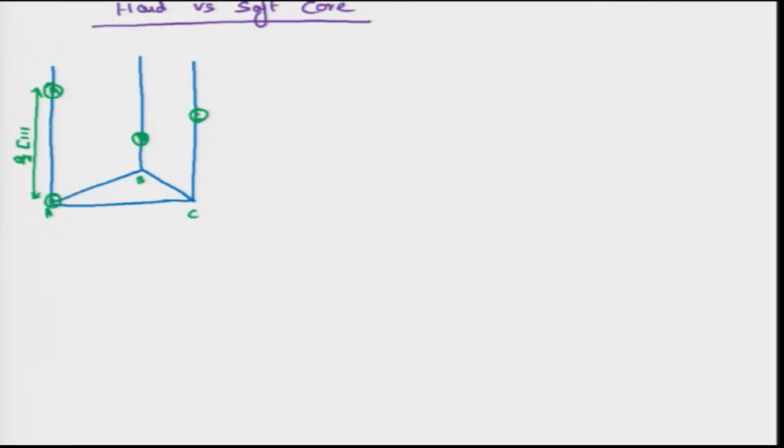So, this is the A row and here the atom spacing is a by 2 1 1 1. But with respect to this plane, the difference between the atoms in this layer and this layer is 1 by 3 b, which is equal to a by 6 1 1 1, and this is again 1 by 3 b. So, this total becomes 2 by 3 b,